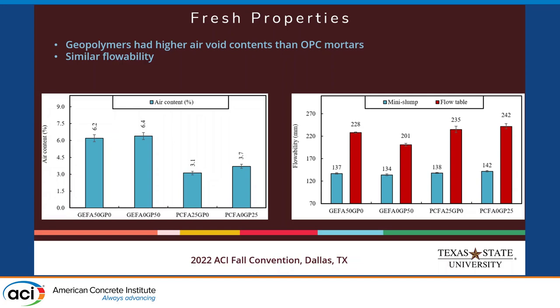Now let's look at some results. For fresh properties, nothing very surprising. The geopolymer system has higher fresh air content compared to the Portland cement-based system, because of the nature of geopolymer — you have much more liquid, so that's why you have more air by weight. For the flowability, we did mini slump and also flow table. Essentially, both systems are very flowable. As long as you do a good mix design, we do not expect any workability issues for this type of matrix.